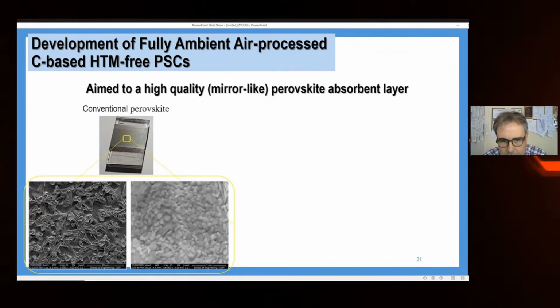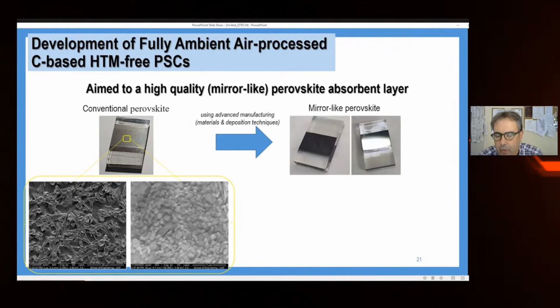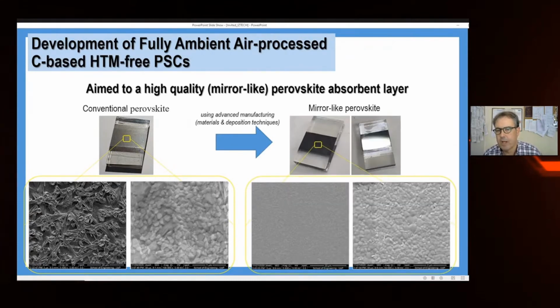We have a conventional perovskite made with perhaps spin coating, and you can see a lot of pinholes here, many gaps. It is not uniform in low magnification. You can see in higher magnification we also have some pinholes, and the quality of the perovskite is not so good. If you follow some advanced manufacturing methods and materials and also some deposition techniques, you can see on the other hand that we have a very good quality of perovskite, a very homogeneous film, and the grains of perovskite are very, very smooth and very good.